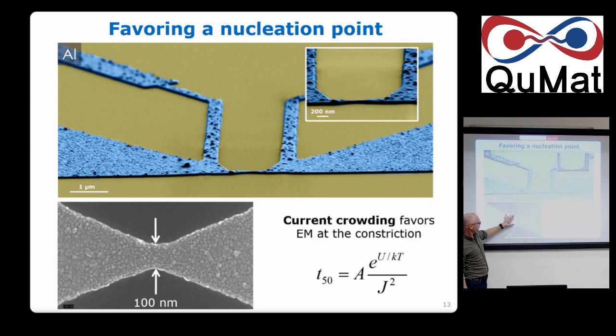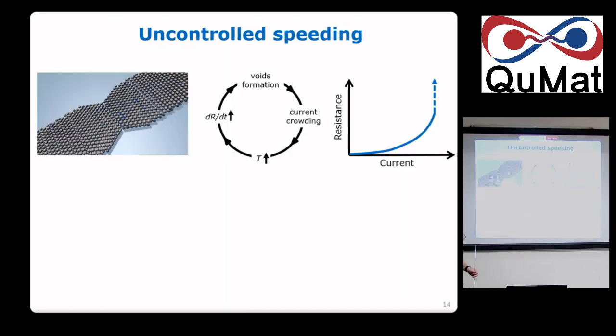We make a small constriction, a few grains, and we know that here the current density is maximum. Okay, so it's going to fail there, and so we know what to look at, because if you do STM, you know how difficult it is to navigate in a sample of 1 millimeter size. It's too big. So now what you have to do is apply a big current and see how the atoms move. Okay, it happens it's not that easy, because once you start moving the atoms.